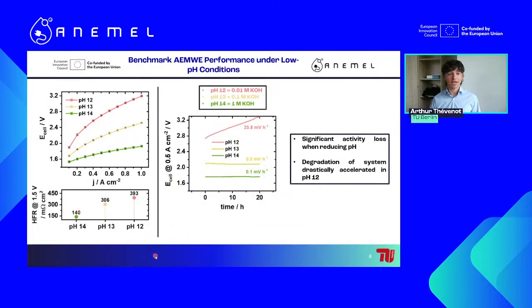So now, beginning the actual study, beginning the actual results. First, to have a scope to understand what's exactly going on when you go to lower pH, we tested this benchmark AEM water electrolyzer under low pH conditions: at 1 molar KOH, pH 14, with 0.1 molar KOH, pH 13, and then 0.01 molar KOH, pH 12. The activity, the performance, is shown over here.